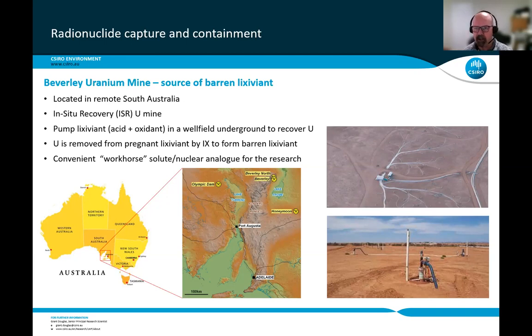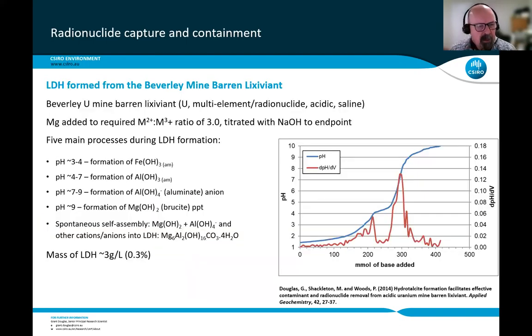But each time, you then begin to build up a quite substantial burden in terms of radionuclides and other trace elements or contaminants. But what this formed for us was what I've called a convenient workhorse solute. Because given the uranium in it, but also the amount of daughter radionuclides, it formed what we like to term a nuclear analog for the research that we conducted. So what actually happens when you form a layered double hydroxide from this barren lixiviant, which contains uranium, a whole range of elements, including radionuclides, it's acidic, and it's saline.